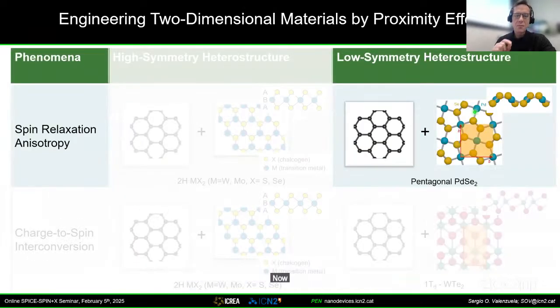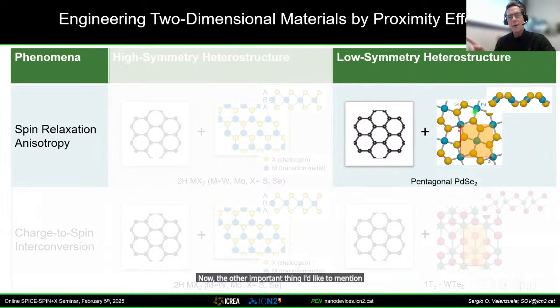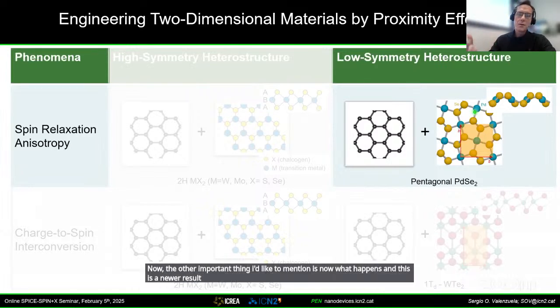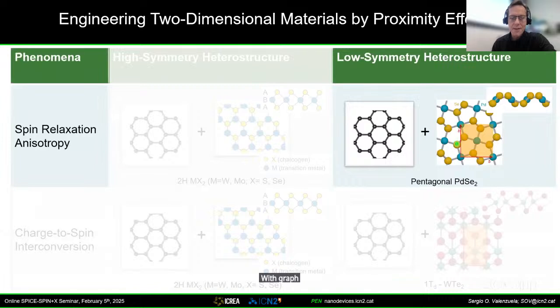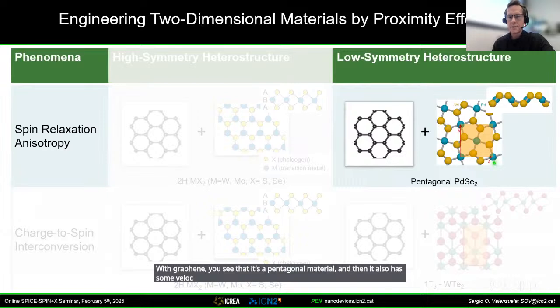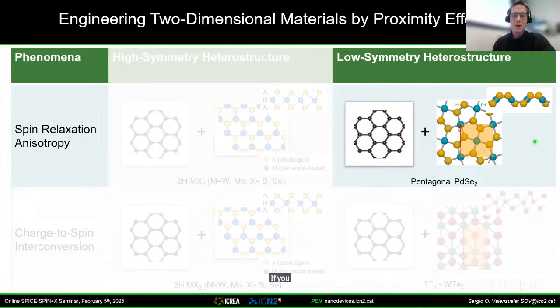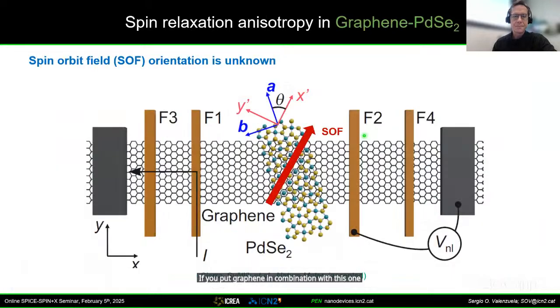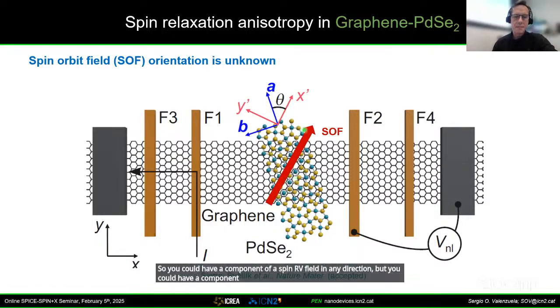Now, the other important thing I'd like to mention, and these are newer results, is what happens when you have a transition metal dichalcogenide which is anisotropic. And we selected palladium diselenide for 2 reasons. It doesn't share any symmetries with graphene. You see that it's a pentagonal material, and it also has some rugosity along the A-axis. If you put graphene in combination with this one, you break all of the symmetries. So you could have a component of a spin orbit field in any direction, including a component in the plane. So the situation is going to be very different in this system.